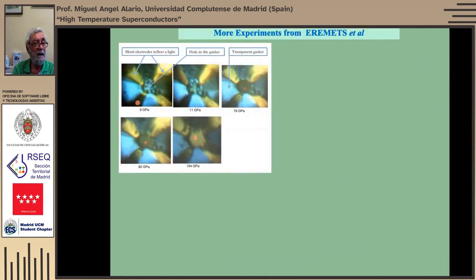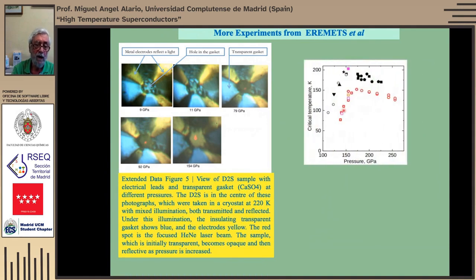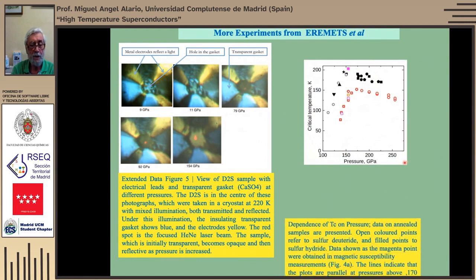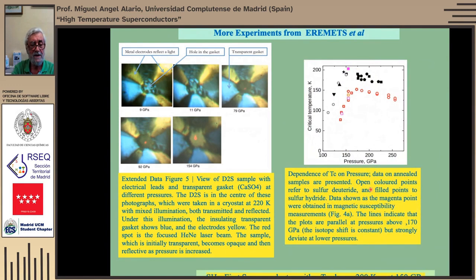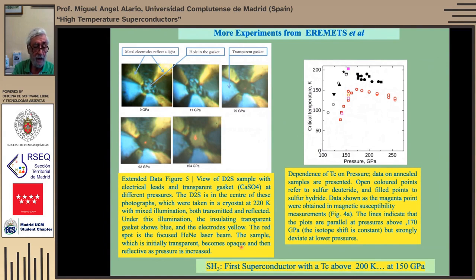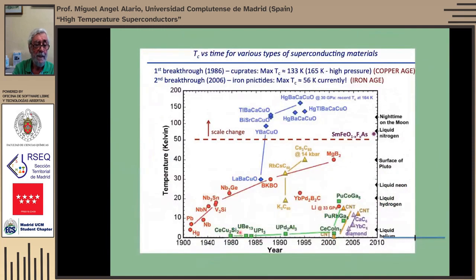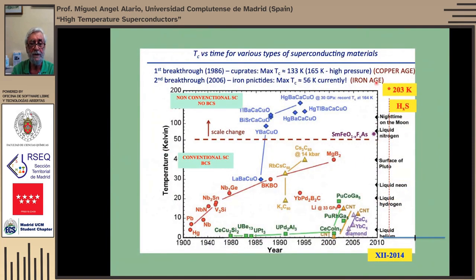So, here again, you see these are the contacts to make the measurements in the diamond anvil cell. With these changes in color, you can do spectroscopy, and in fact, you can see how the critical temperature changes with pressure. So it is clear that SH3 is a superconductor with a temperature above 200 Kelvin, but at a very high pressure. Now we are in this region. This came out in 2014. But then, again, it's conventional.